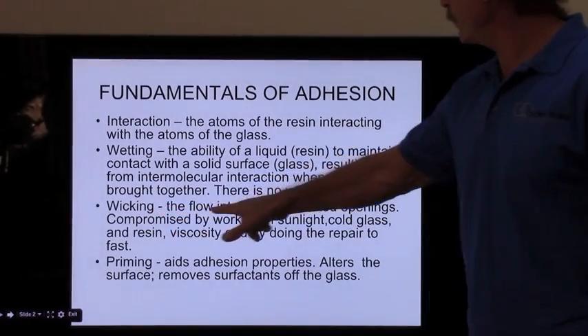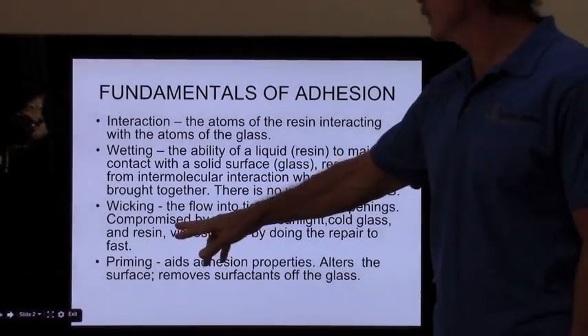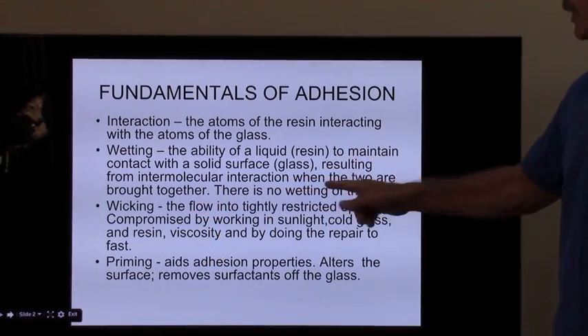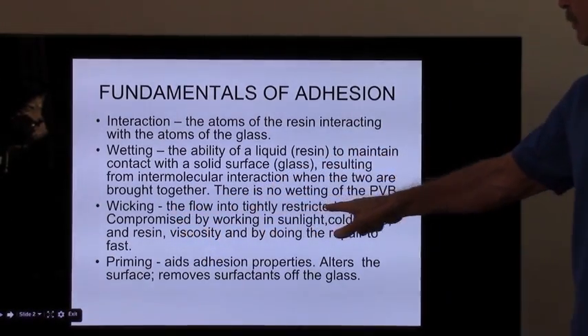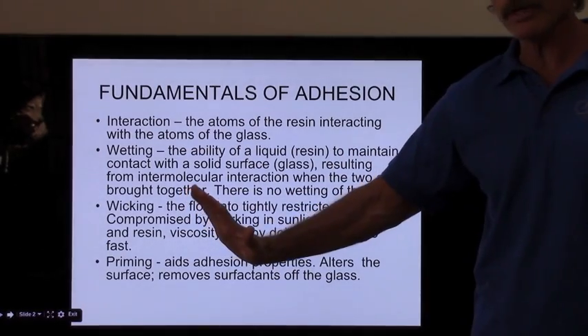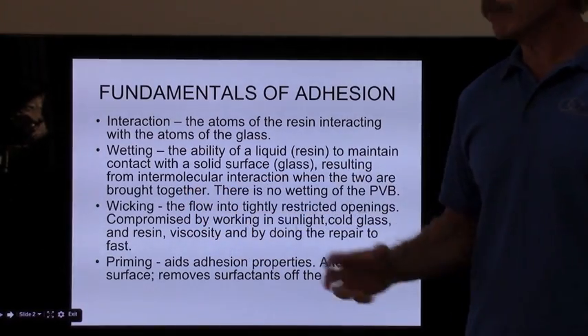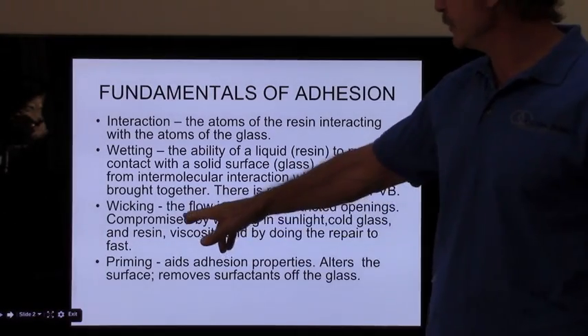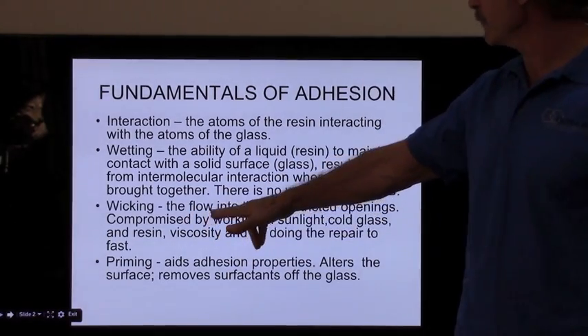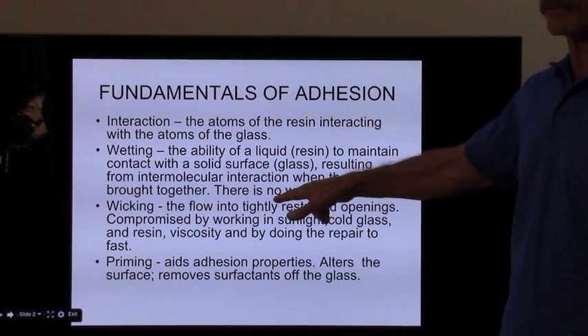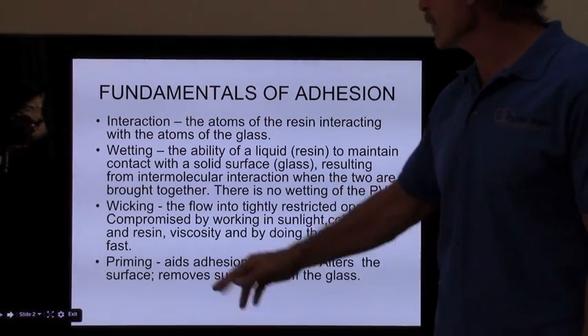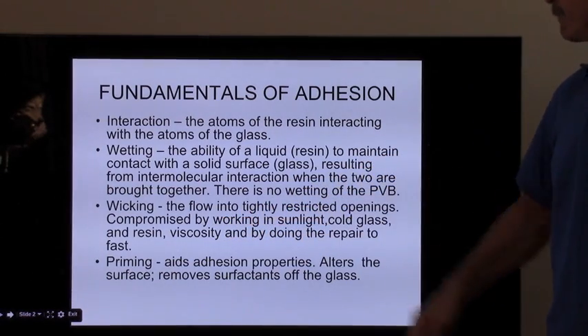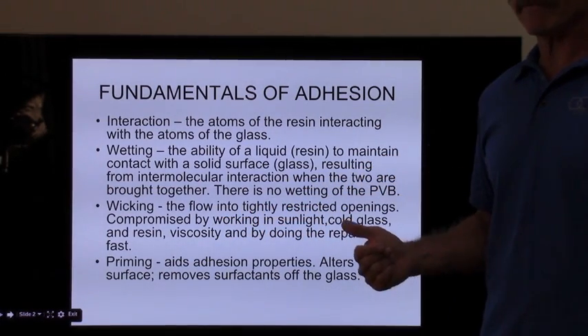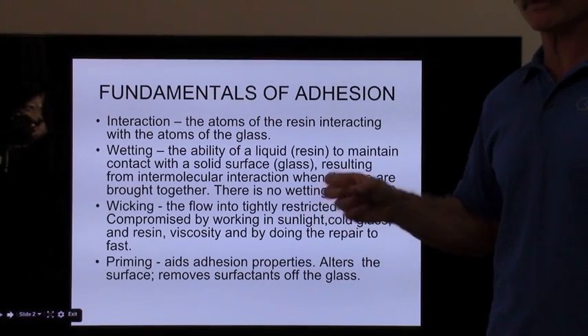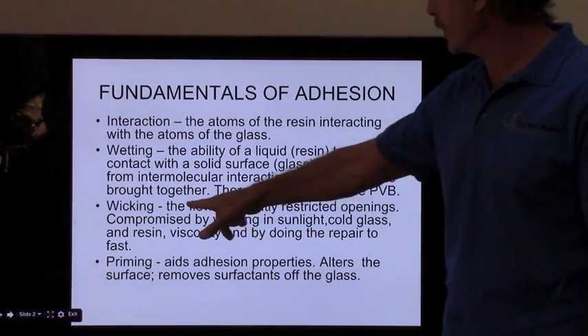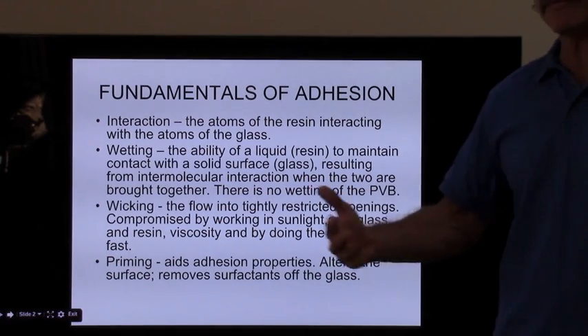Wicking. Wicking is the flow into tightly restricted openings. You have an advantage when you fix stone breaks because you're pushing it in under pressure. With a stone break, you have a closed surface and you have a piston cylinder, where the piston is pushing the resin, and that's how it gets into those tightly restricted openings. It's much easier to get into those openings. It can be compromised by working in sunlight, because as soon as the UV hits the resin, it will start to cross-link and thicken, and it won't wick. It won't get into those restricted places, and then you have a compromised repair.